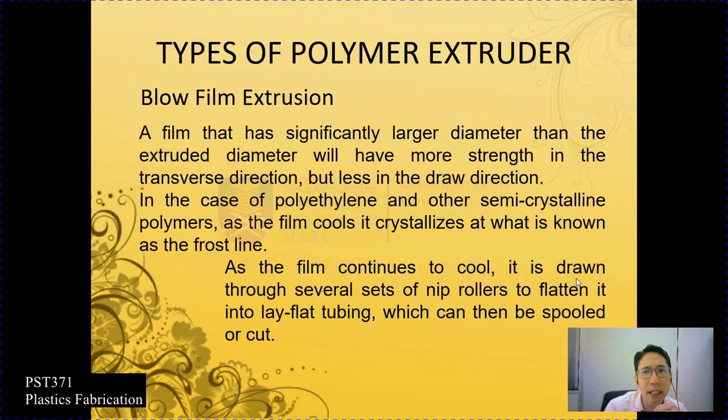A film that has significantly larger diameter than the extruded diameter will have more strength in a transverse direction but less in draw direction. Ini vice versa lah. Okay, kalau tadi draw direction kuat, yang ni transverse direction dia akan jadi lebih kuat.